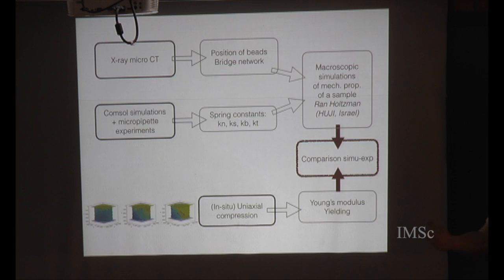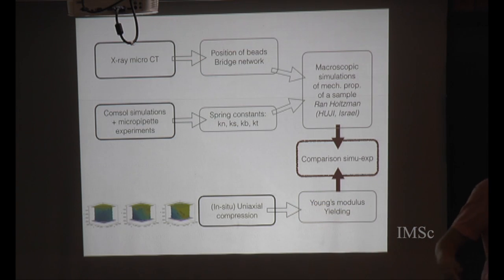And so basically the end result of this, which is still a work in progress, we tell him what the constitutive relationships are between individual beads. We tell him the X, Y, Z starting coordinates of the beads, and we ask him to predict the deformation that will occur. And then we truth test that with our X-ray tomography observations to basically try to connect those two things from the microscale to the macroscale.